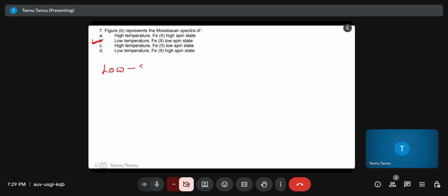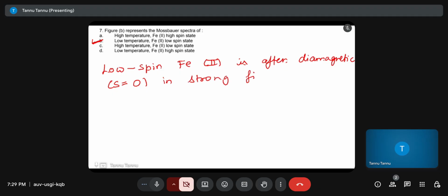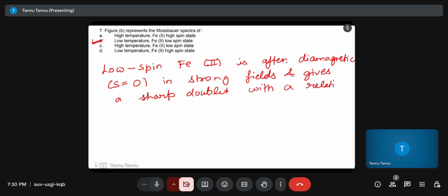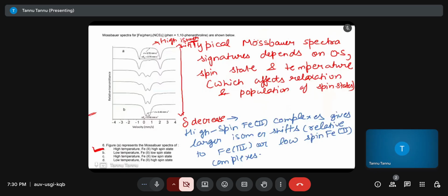So your low spin Fe2 is often diamagnetic in strong fields and gives a sharp doublet with a relatively small isomer shift and small quadrupolar splitting. So you can see that there is a very small quadrupole splitting as compared to this.